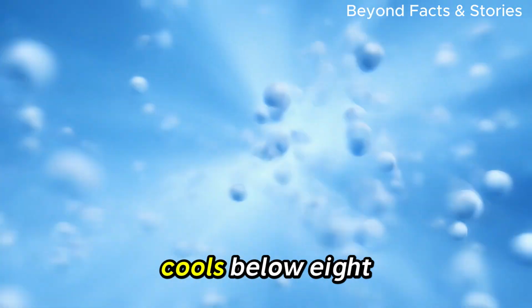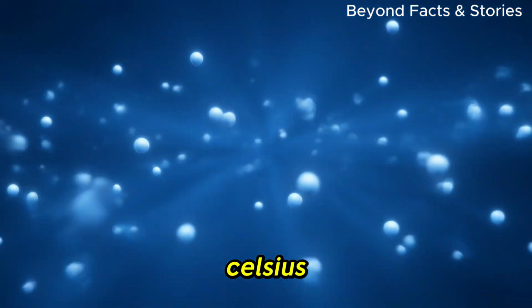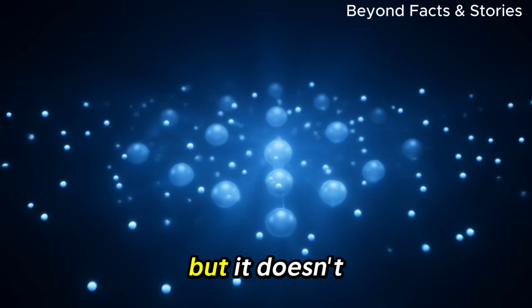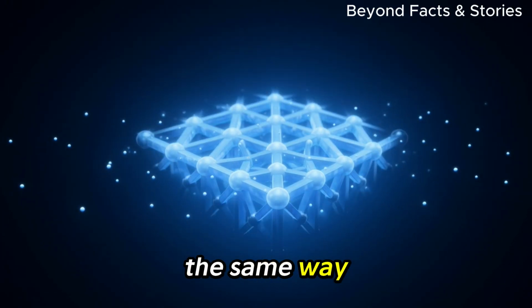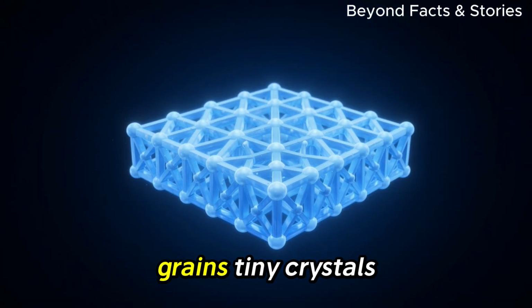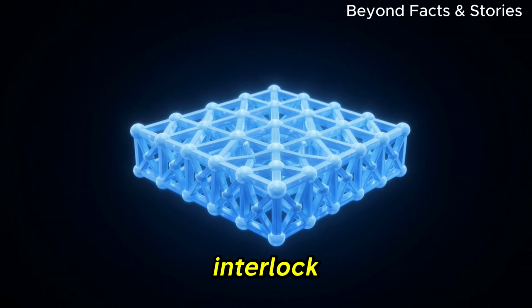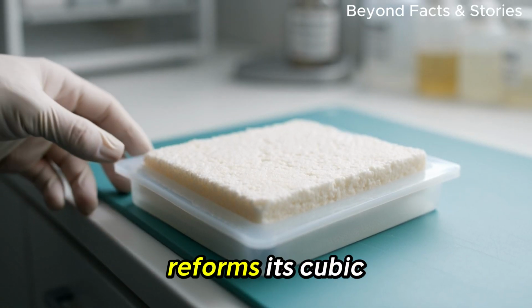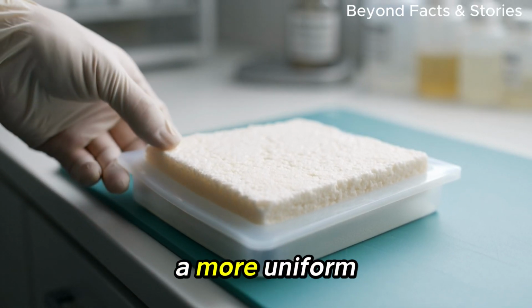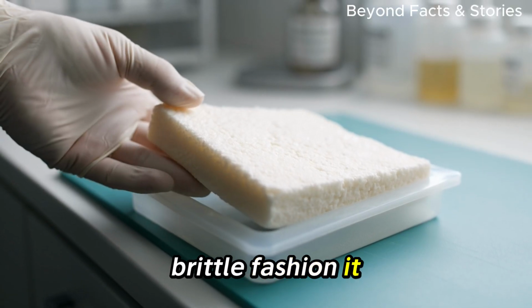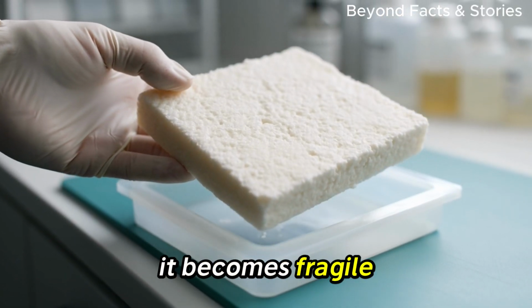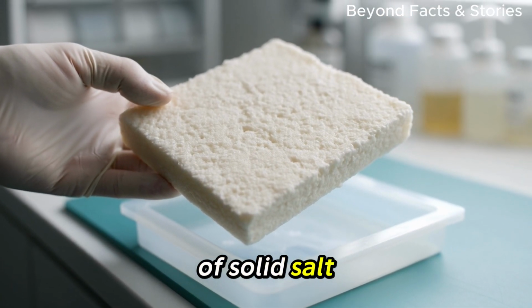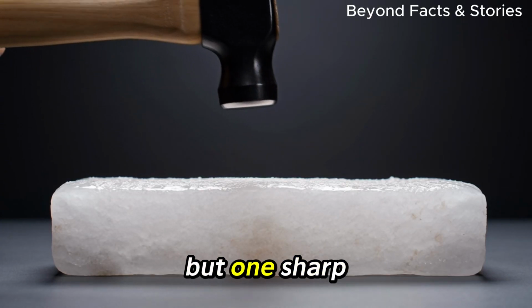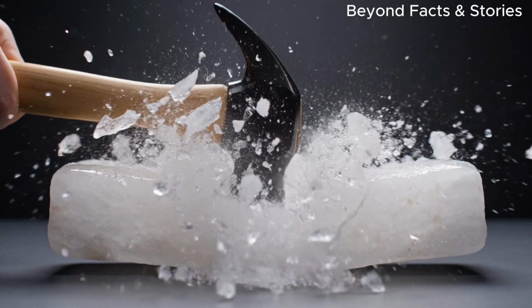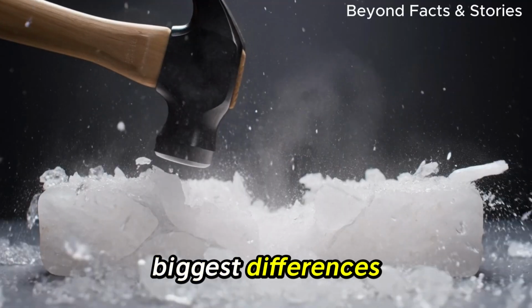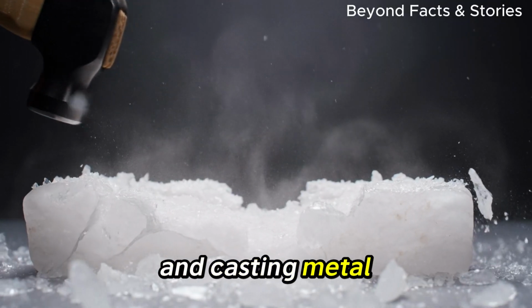As molten salt cools below 801 degrees Celsius, it begins to solidify. But it doesn't shrink and solidify the same way metals do. Metals often form grains, tiny crystals that grow and interlock. Salt, however, reforms its cubic crystal lattice in a more uniform, brittle fashion. It doesn't become tough, it becomes fragile. A cast bar of solid salt would look impressive at first glance, but one sharp impact, and it could shatter. This brittleness is one of the biggest differences between casting salt and casting metal.